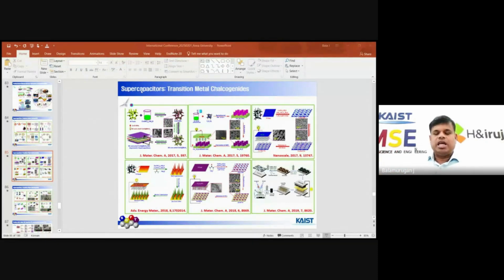And finally, we use the nickel foam as a current collector to grow the active material, like wire type or sheet type material. With wire type or sheet type material in vertical directions, the electrons easily penetrate, and then more active sites are available. One good thing here is that we avoid the binders. Then we get higher performance for energy storage like supercapacitors.